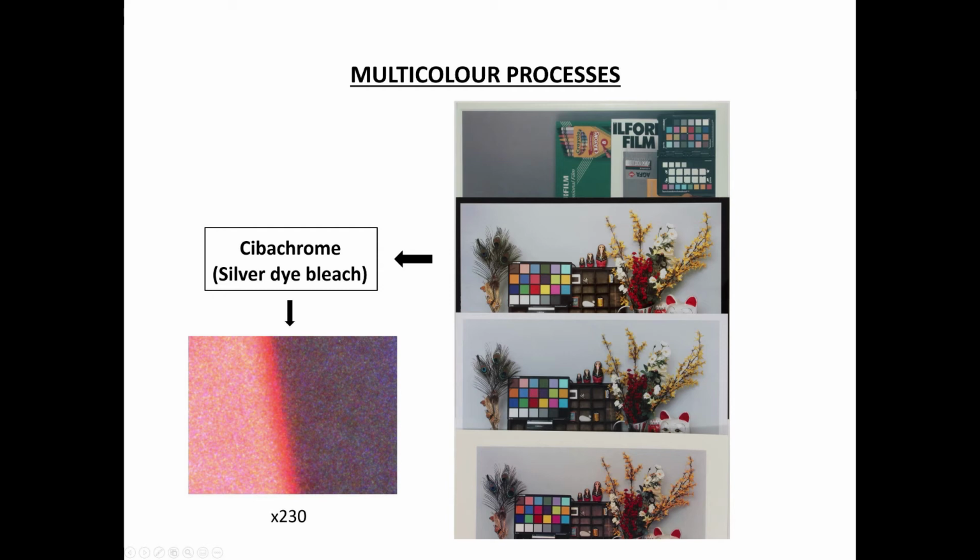Cibachrome was introduced in 1963 and became Ilfochrome in 1992, which was around until 2012. It was a more expensive process than chromogenic printing and produced sumptuous vivid colours with an almost metallic lustre, and many Cibachromes or Ilfochromes were glossy. It was initially made on pigmented white cellulose acetate and later on resin-coated paper or white pigmented or voided polyester. The dyes in Cibachrome are more stable than chromogenic processes, although the papers are susceptible to abrasion.